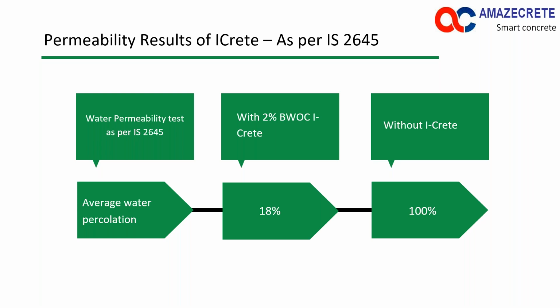When we are talking about iCrete permeability test as per IS 2645, the average percolation of water when 2% is used comes down to 18%, and without iCrete it becomes 100%. So there is a tremendous reduction in the permeability.